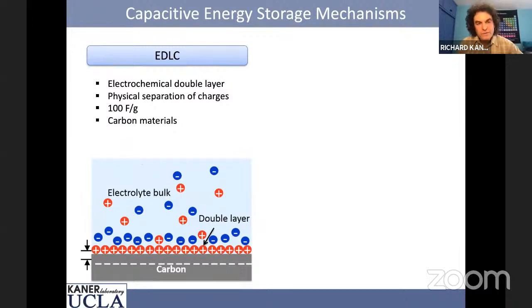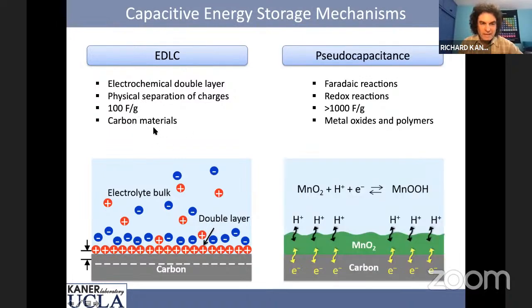One of the neat ways of doing that is looking at electric double layer capacitors. And so what we want is materials that have more energy storage than carbon. And a good one is manganese dioxide. Manganese dioxide is a material that's used in alkaline batteries. So if you go to the store and you buy, my favorite store is a dollar store, you can get about 10 of these for $1. And what they are, they're filled with manganese dioxide and a lot of carbon. They often have 30 to 40% carbon because manganese dioxide is an insulator. So they need carbon black just to conduct.